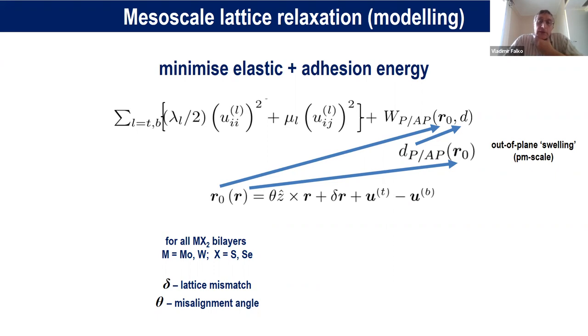So the starting point, before this relaxation is done numerically, is that we implement the Moiré periodicity by this dependence on the coordinate, which is determined by a small misalignment angle, accounted as rotation of one crystal with respect to another, and also by a small mismatch of the two lattices of the two materials. For the combination of transition metal dichalcogenides that we look at, this parameter delta is less than 3%. And for the same chalcogen bilayers, delta is even less than 1%.